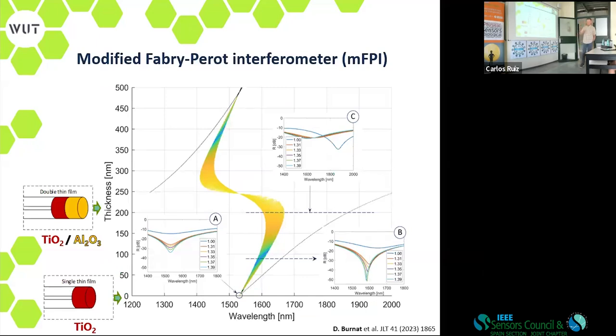But quite recently, we decided to make a step backward, to limit the number of layers. So when there's one layer on the fiber, there's a covering interferometer. But this interferometer is sensitive to refractive index, so the dip of the spectrum changes with refractive index, and it shifts towards longer wavelength when something accumulates on the surface in the layers. But when there is another film of lower refractive index on top of it, we can tune the reflection conditions, so we can make this interference pattern very, very deep. And it started to shift with index as well. So it shifts with deposition, with formation of the biofilm on the surface, and it's deep already. So we have a lot of benefits of this configuration, this film for the cell.